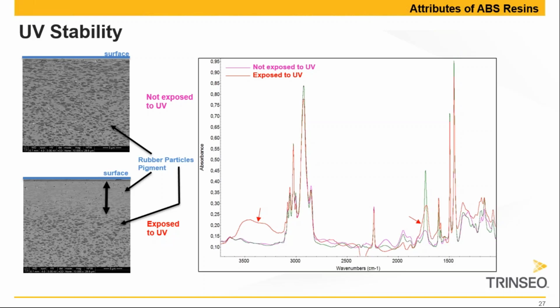And the staining process acts on the double bonds that are present in the rubber. Now, because of UV exposure, these double bonds are gone. The high energy of the UV light starts to cross-link the rubber and destroys and consumes all the double bonds. So the staining process cannot happen anymore. And that's why the rubber particles are not visible anymore, but they're still there. So in effect, you have in this case a layer of about 10 microns thick of completely cross-linked rubber particles. So that layer will act as SAN, as a brittle layer.